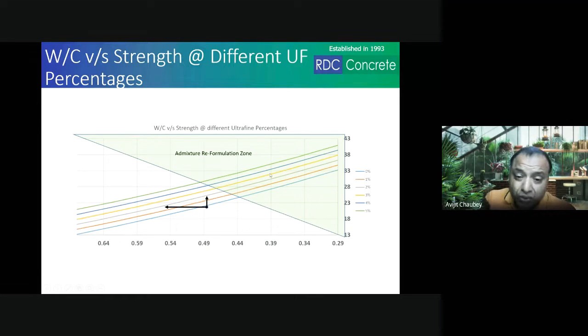So don't shy away, because what will happen is, if you are making a concrete without ultrafine at, let us say, 0.49 water cement ratio, and then at 0.49 water cement ratio you want to use 5% ultrafine, that means at this point you will need to reformulate your admixture. You may need to go with a high end PC, because these materials are much finer than cement particles. You require a higher effort for dispersing them.